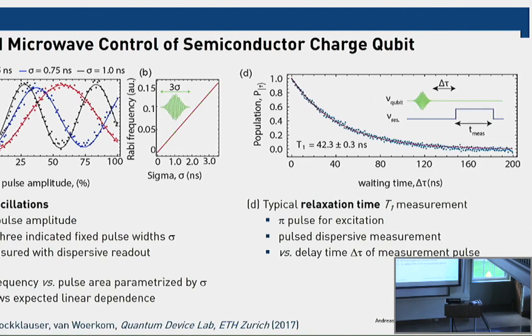Obviously, once you've done Rabi oscillations, you can define pi pulses and pi half pulses. So here's a pi pulse: you can apply a pi pulse and then measure the energy relaxation time of a charge in this quantum dot in a typical T1 measurement, just the standard circuit QED style measurement, and extract relaxation times. And what is nice now is that you can start to do experiments in which you extract properties of these semiconductor quantum dots quite accurately, using circuit QED style measurements of the coherence properties.